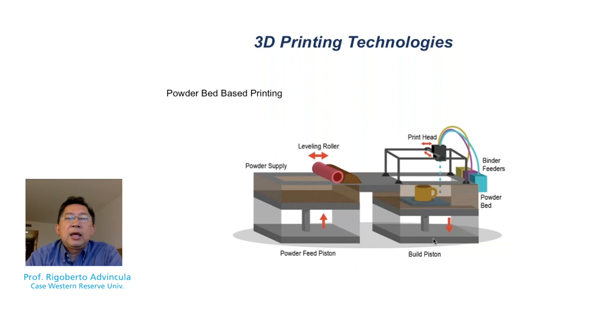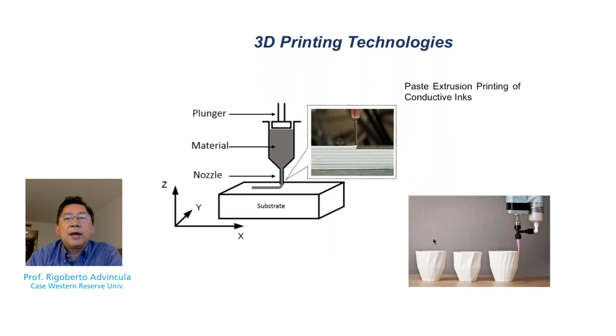with the fresh printing. Almost similar is powder bed based printing. The powder supply and leveling roller allow you to give a uniform fresh layer. However, instead of a UV light or a UV curing mechanism, you deliver the curing component with the print head. This combination of materials means that the active component could be part of the powder, or it could be part of the resin material that is delivered by the printhead or is cured by UV light.